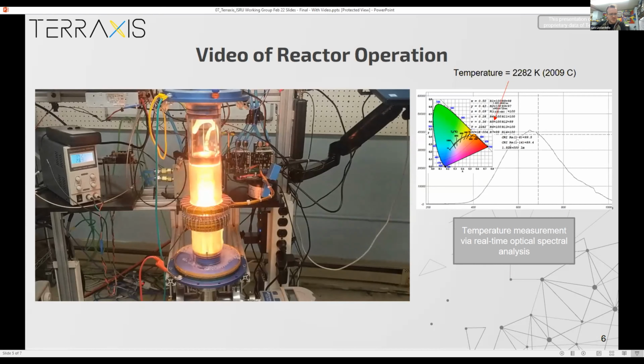Yeah, so this is a video of our prototype running a couple months ago. You can see the crucible is glowing white hot in the center of that chamber. And that chamber is being maintained at a reduced pressure. Not hard vacuum, but a decent vacuum. And the way we measure temperature, because it's a very, very high temperature process, is actually optically. So we have an optical temperature probe that will measure essentially the black body radiation output of the crucible and then give us a readout.